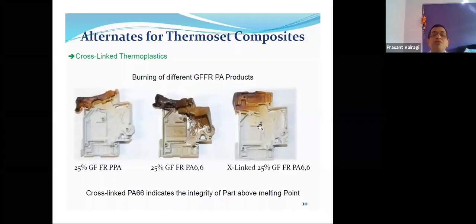Now, the flame is applied to all these three components. If you see the same material, that is 25% glass filled FR nylon 66, without radiation cross-linking, the component has molten, burnt, and completely collapsed. Whereas the melting point of nylon 66 is about 260 degrees centigrade, and if you go for PPA, the melting point is about 320 degrees centigrade. With the same reinforcement, I have applied the flame, and it has also burnt and deformed, not as bad as nylon 66, but it has deformed to some extent.